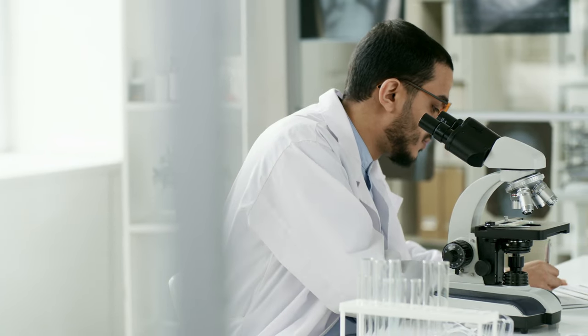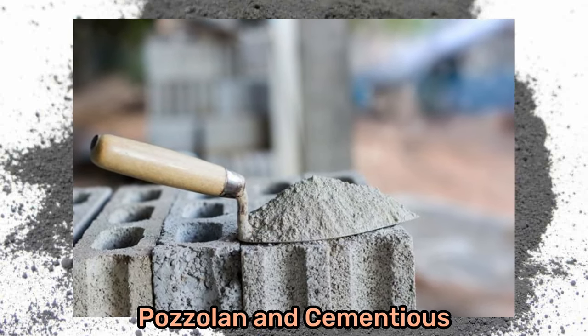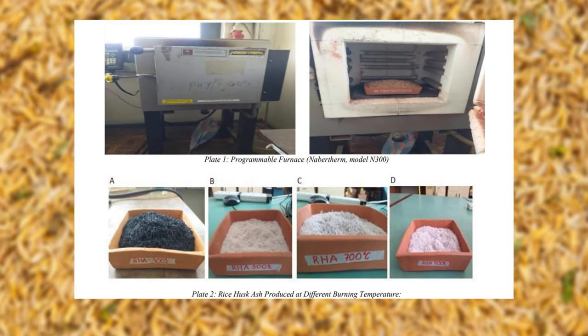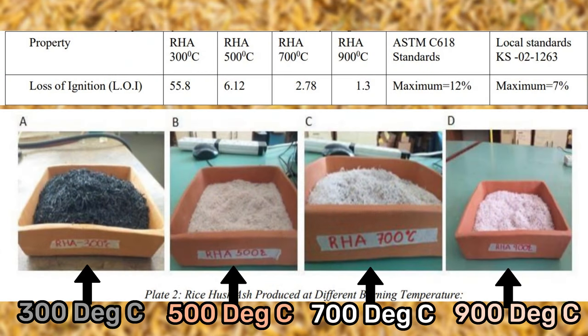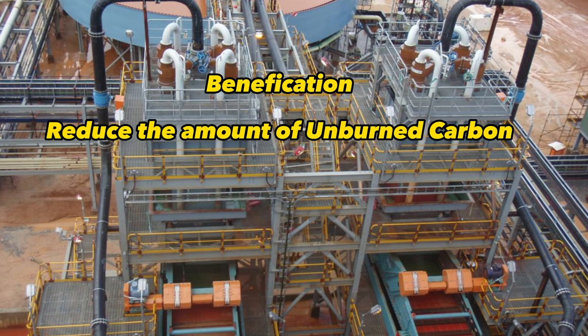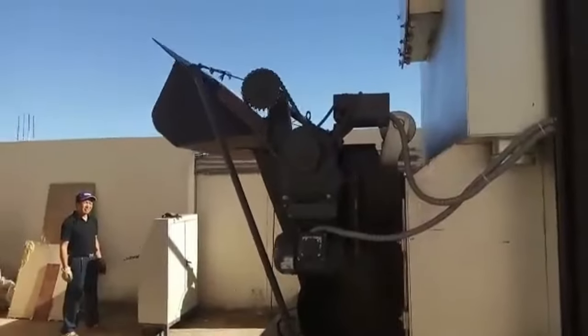The form of silica can be easily tested in the lab. The amorphous silica is a very good pozzolan and possesses high cementing property. Similarly, the white or black color of the ash is determined by the content of carbon, which is determined from the loss on ignition test. If carbon is low, then the color of the ash is white, whereas it is black for higher carbon content and loss on ignition. This carbon content should be low for using it for its cementitious property, which works the same as that of OPC cement. The carbon content can be reduced by a beneficiation process, but it adds extra cost. So, burning of rice husk should be regulated for the best product, and produced ashes should be tested for their properties before using. Hence, knowledge of this is essential.